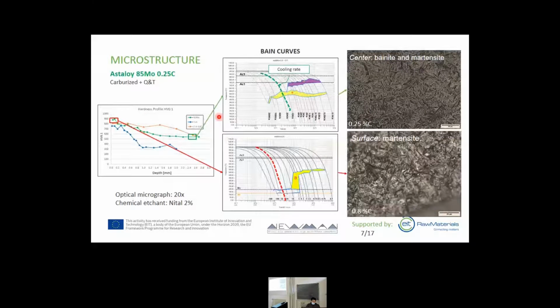The microstructural analysis confirmed the hardness profile. In fact, looking at the Astalloy 85MO, we have a martensitic bainitic structure at the center, while due to the different content of carbon and the different cooling rate, the microstructure is 100% martensitic at the surface.